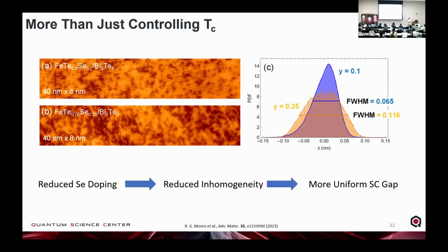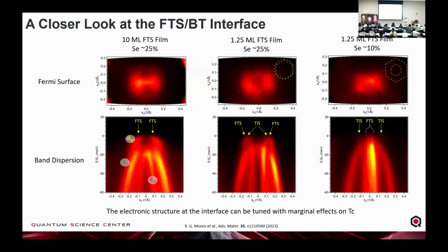And we can look at it in STM and see that as we start reducing the doping, of course, we're generating much more uniform films, and this uniformity will help us improve the size of the superconducting gap, and it'll help us reduce any of these trivial states that might appear in the superconducting gap. But what's important is if we really zoom into the Fermi surface, here is a thicker film,